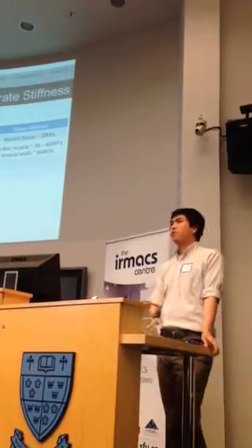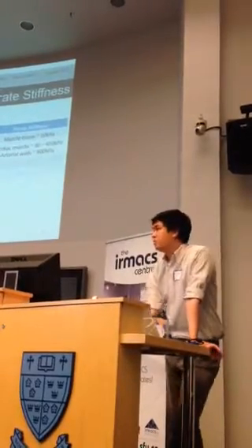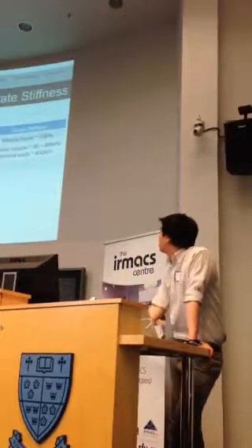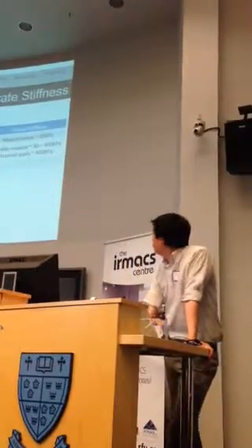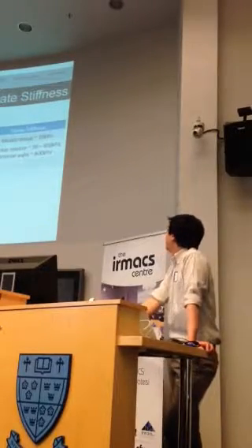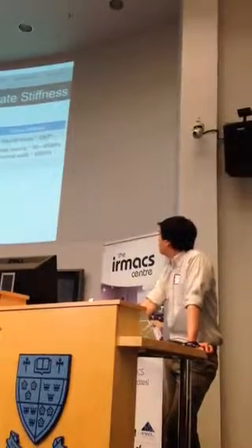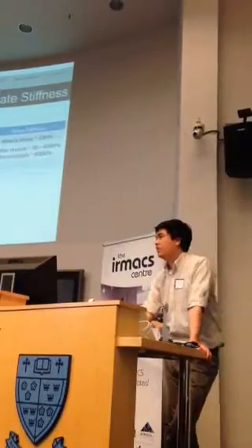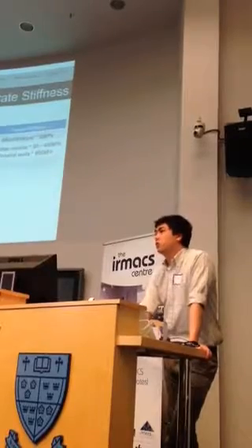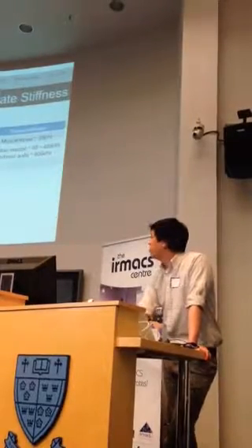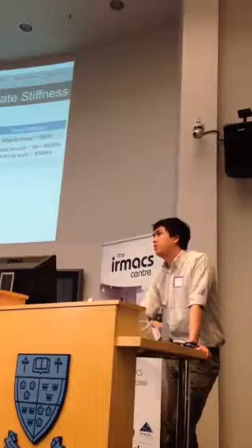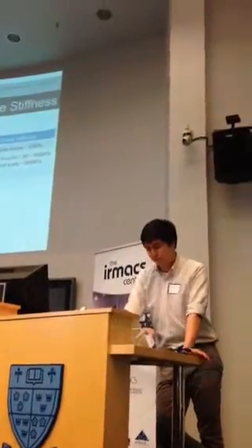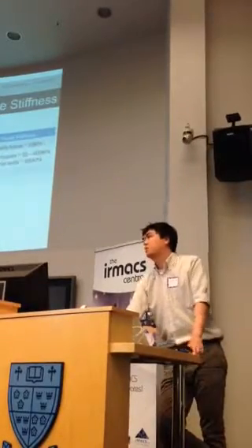Just to give you a feel of what the stiffnesses are like in the natural human body, muscle tissue is approximately 10 kilopascals. Cardiac muscle under physiological strain has a Young's modulus between 30 to 400 kilopascals. Arterial walls, 800 kilopascals. A very interesting thing to note is that all tissue culture work being done in the lab right now is on tissue culture dishes that are typically made of polystyrene, and it's very stiff. It has a Young's modulus range between 3,500 to 4,000 megapascals.